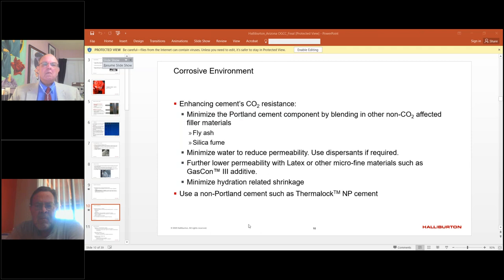I did mention a little earlier the use of latex for permeability reduction of the cement. We would normally see about a 0.1 millidarcy on a 15 pound per gallon cement. And if we further reduce that, it would inhibit the carbonic acid actually invading the matrix of the set cement itself. In extreme conditions where we have very high CO2, wet CO2, we actually have a selection or a series of products which contain no Portland cement at all.